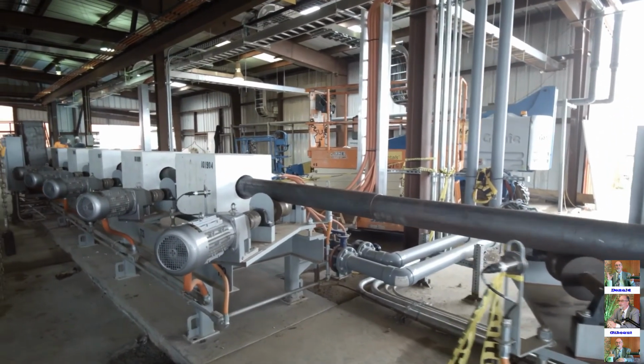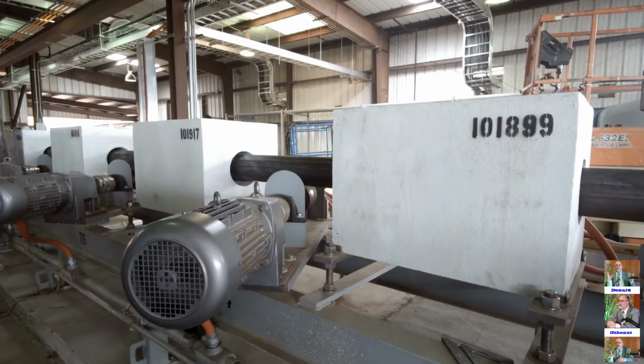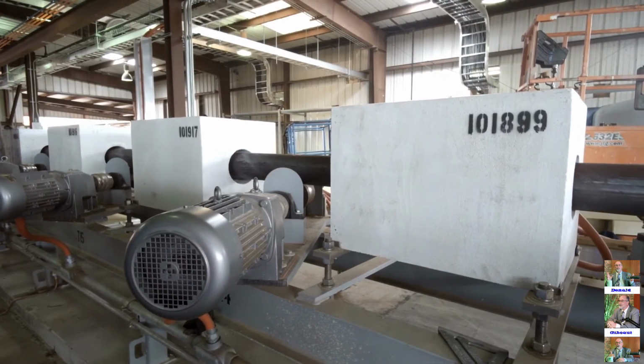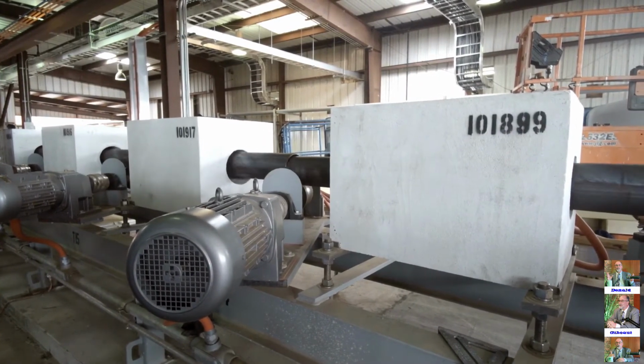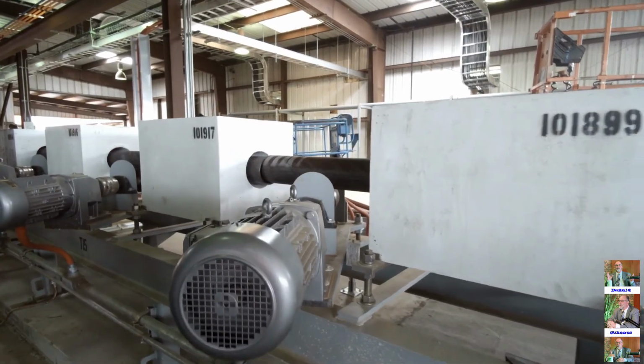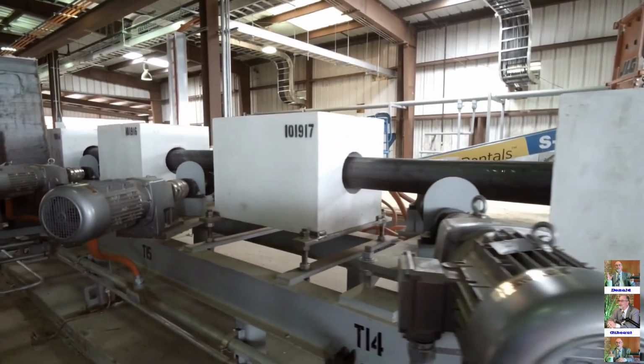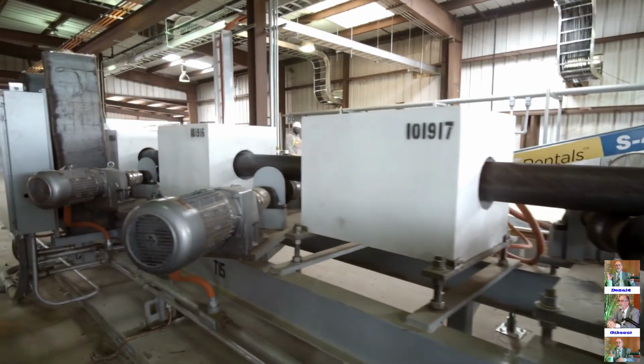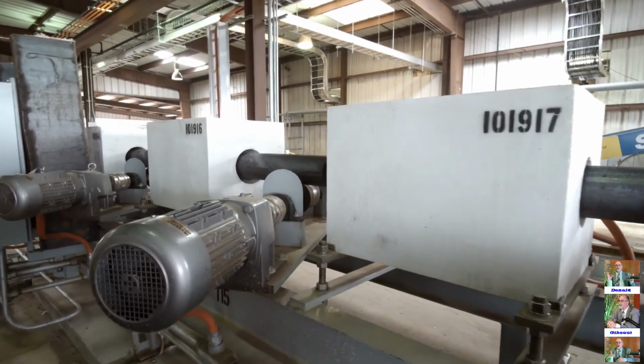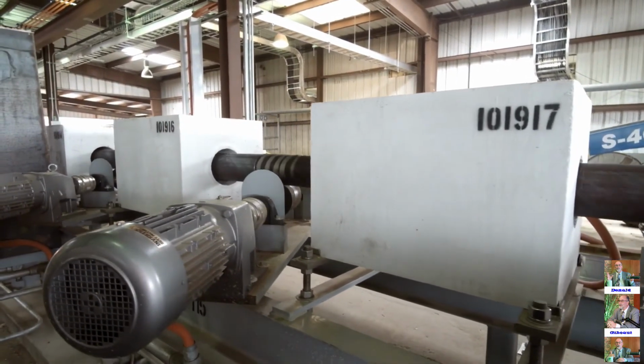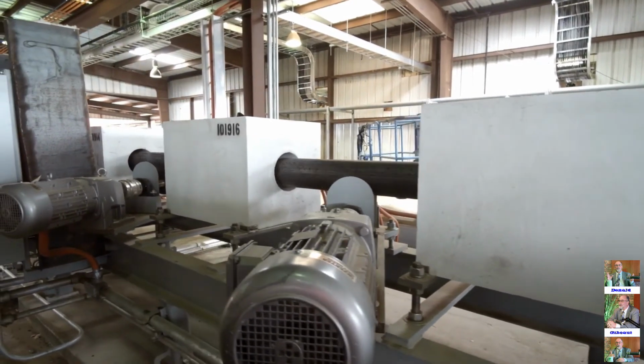And like we talked about that current crowding, we can have, as a rule of thumb, up to a half inch and not really get into overheating the ends. And we're lower frequency here, as we showed with the FEA. That also helps with that current crowding when you produce a gap between the pipes. But you can see here it's very precision controlled.